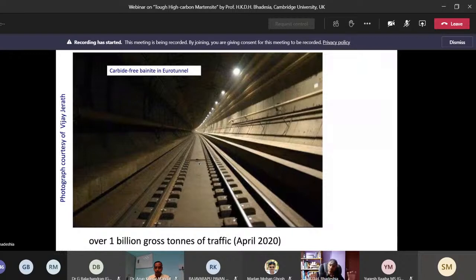Now, rails are inspected regularly, and they tend to develop fatigue cracks from the surface. So what they do in ordinary rails is that they grind some of the surface away so that the fatigue cracks are removed and they don't penetrate. In this case, we do not require that grinding because there are no hard particles to induce that fatigue. It's a very fatigue-resistant structure. And furthermore, the austenite near the surface, which gets deformed by the passage of traffic, will actually harden the surface by forming this fine, untempered martensite.